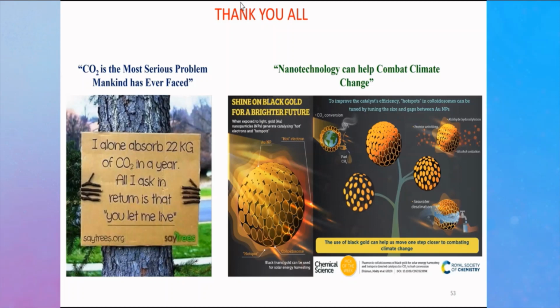How does the catalytic activity increase? This is a question by Bharat: how does the catalytic activity increase after burning of the carbon in sequential cycles? What I said is what we thought, that when catalytic activity goes down, CO2 gets converted into carbon, and that carbon is coating the defected site. And if that is the thought, then the best way is to treat that in air and burn away the carbon. But if you burn away the carbon, what you said is correct. Why will it increase the catalytic activity? It's not because of the carbon.